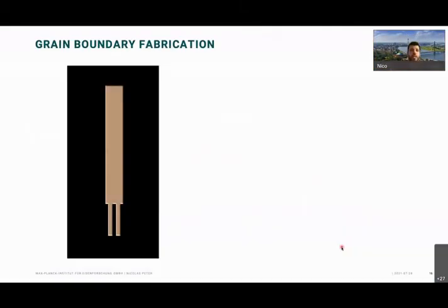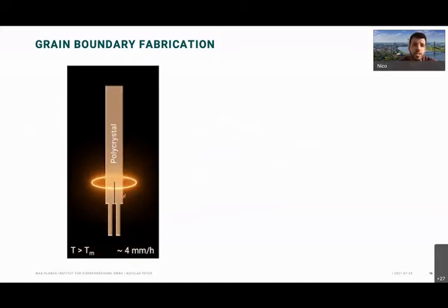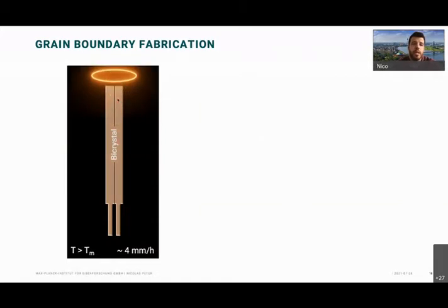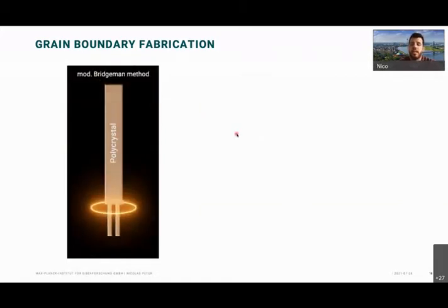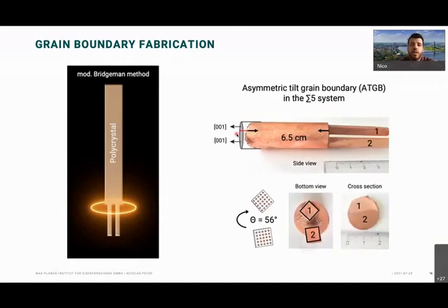So how did I fabricate my grain boundary? I did this with a modified Bridgman method. You have a polycrystal, like shown here. You put two single crystal seed crystals at the bottom, and then you heat it up. So you have a polycrystal that then slowly becomes a bicrystal. This black line here indicates that. How it looks experimentally in real life is shown here. We have the two seed single crystals here, and then the bicrystal with the grain boundary running fairly straight, with two common 001 growth directions, or zone axis later in the TEM.